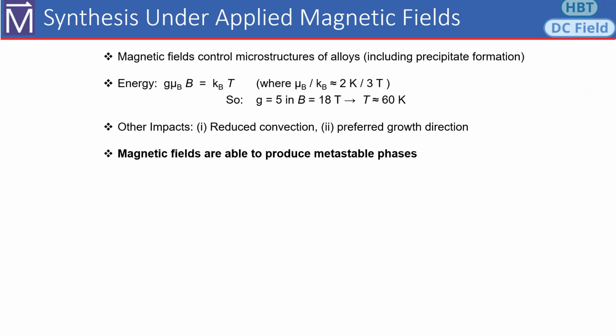But that's not all. This concept that a Tesla is a Kelvin may not really be spot on all the time, especially if the g factor is larger. So for lanthanides, for example, in a field of 18 Tesla, it starts to become more like 60 Kelvin. If you can pull your growth temperatures down, maybe using low melting temperature eutectics, then you start to get into a regime where, remember your binary phase diagram, that's temperature and chemical composition, can start to have a new axis coming off of it. I think there's lots of opportunities there.